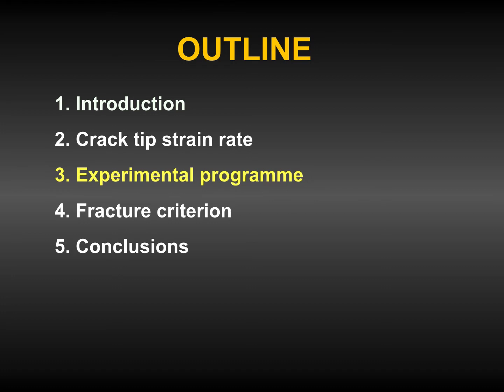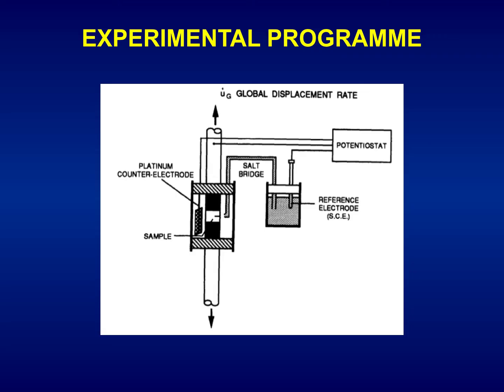With this average of space and time of the local strain rate at the crack tip, or crack tip strain rate, we apply this concept, this computational method, to the results of an experimental program on pre-cracked samples of pearlitic steel tested under hydrogen embrittlement environmental conditions. This is the experimental setup with a potentiostat in a 3-electrode assembly: reference electrode, saturated calomel electrode, a salt bridge, platinum counter electrode, and the sample as the working electrode. We use a cathodic potential, minus 1200 millivolts versus saturated calomel electrode, just to promote hydrogen embrittlement, hydrogen-assisted cracking, environmental conditions.